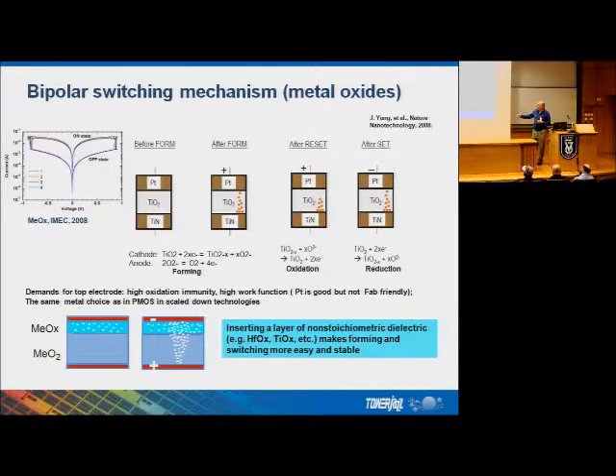So during the forming procedure, there is the reaction of losing oxygen. The material becomes non-stoichiometric, and there is a connection of the bottom electrode with the top electrode. And during reset and set operations, there are actually oxidation and reduction processes in the vicinity of the top electrode. In this case, this is a platinum electrode. So the channel which was built and corresponds to the deficiency of oxygen, that is why it is conductive, is oxidized by reaction with oxygen near the top electrode when there is plus on this electrode. And again, there is a reduction and recreation of the filament if there is a minus on the top electrode. So oxidation and reduction of the filament, which was previously formed during the forming procedure, is the mechanism of operation.